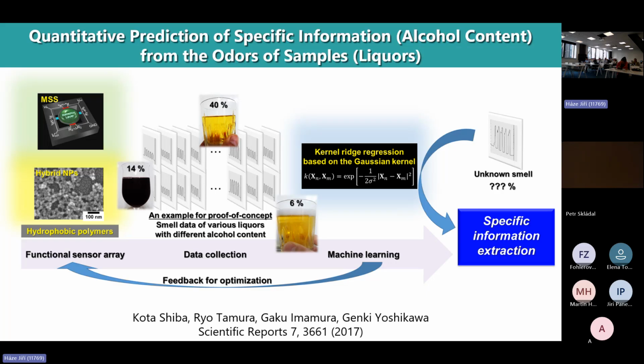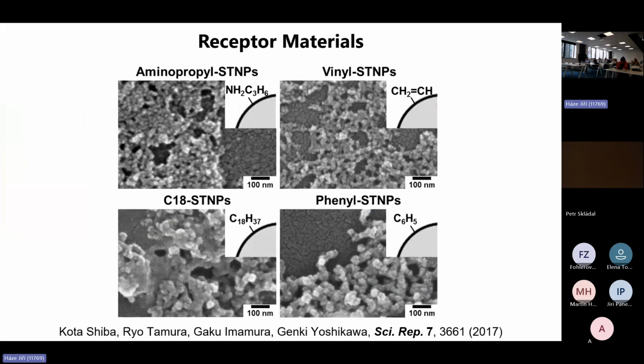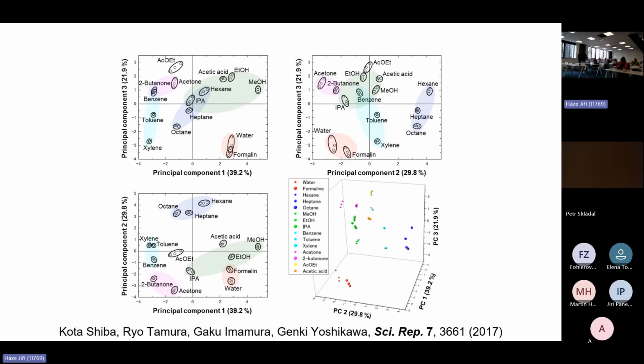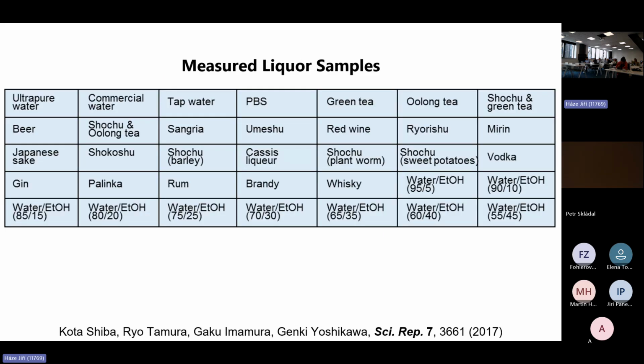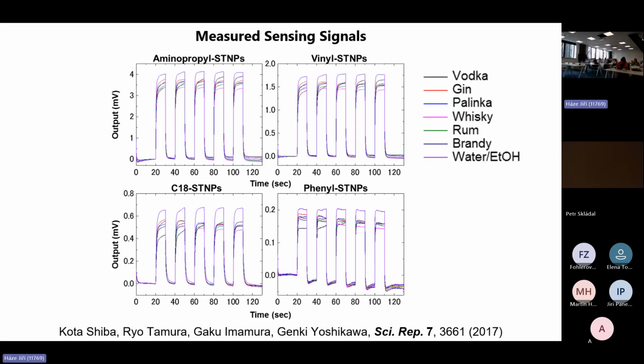And Liu made machine learning models and gave feedback for material selection. We started with nanoparticles with different functional groups on the surface, and confirmed that these combinations can differentiate different types of chemicals like this. Then we measured the liquor samples, in this case 35 different liquor samples. This is a typical sensing signal, where the gas was injected and purged 5 times.